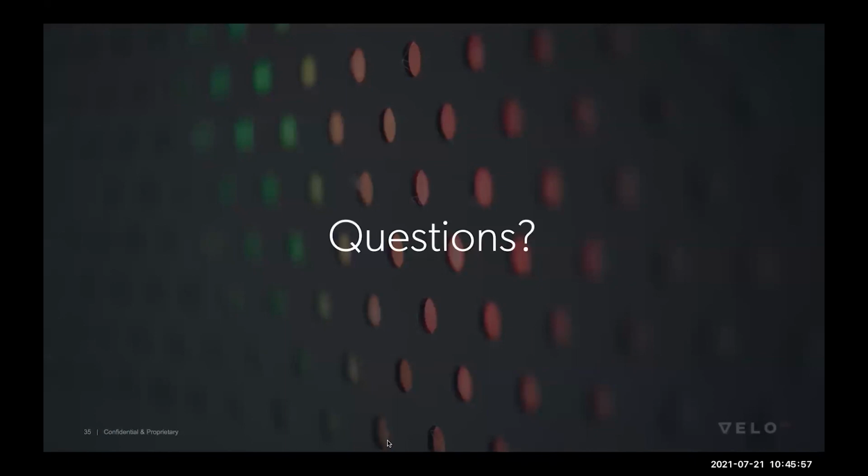There were a couple questions in here for Gene. I think you had a slide on there with a big titanium disc. There are some questions in there about the in-process stress relief. Now, I understand this is a proprietary process, but to the degree that you can talk about it, they're wondering more about it. And does that remove the need to do stress relief after the process is done? I can shed some more light on that. I can't divulge any IP without something like an NDA in place. However, I can say, ultimately, no, it is not eliminating the need for post-processing heat treatment. It's not designed to reorganize the microstructure or provide a significant amount of ductility to the titanium. It's still brittle when it comes out, but it's less brittle.